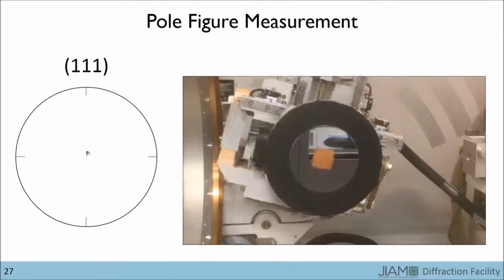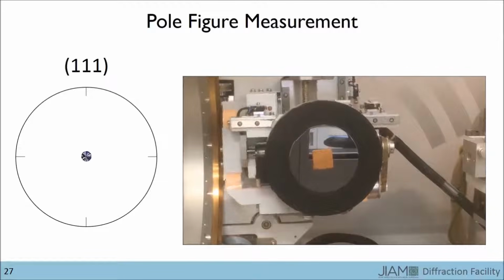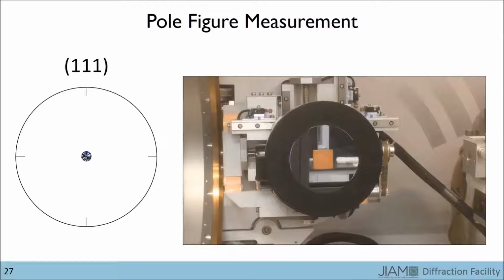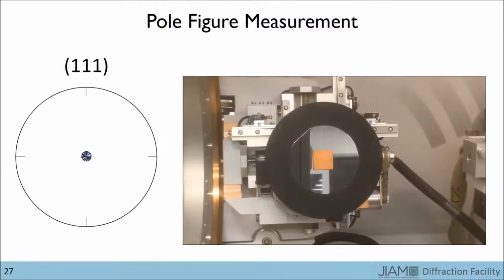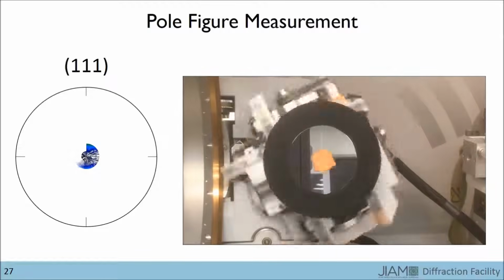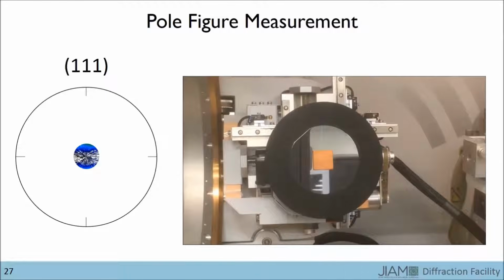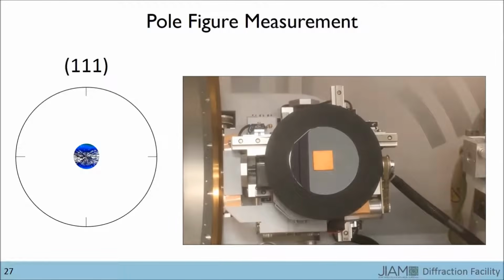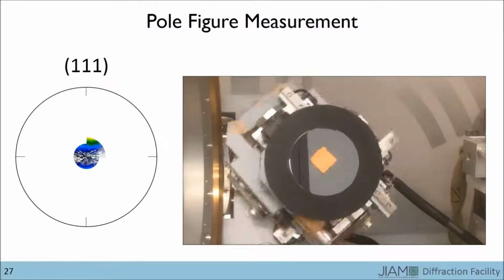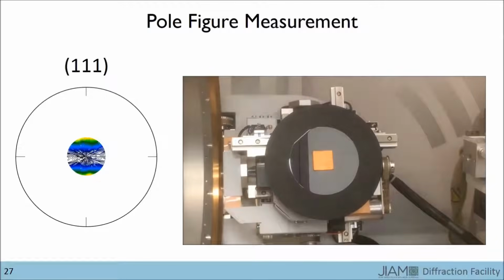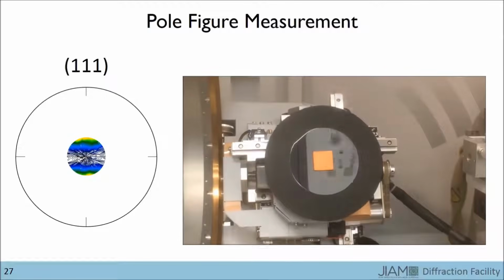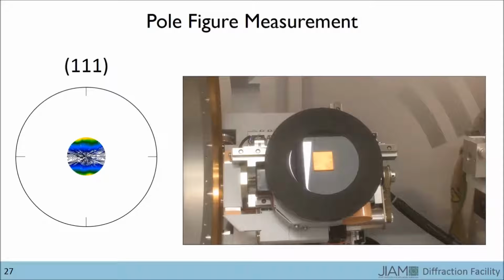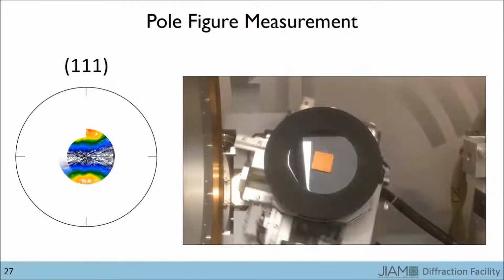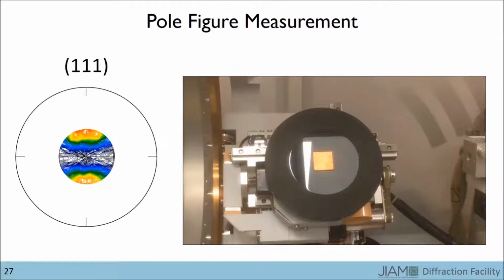As I said, we first rotate along phi and we see almost no intensity on the plot, indicating that there aren't any 111 planes oriented correctly for diffraction. We then rotated a bit back in chi, then rotated in phi again while collecting data. This time we start to see some intensity appear, so some 111 planes are oriented correctly.